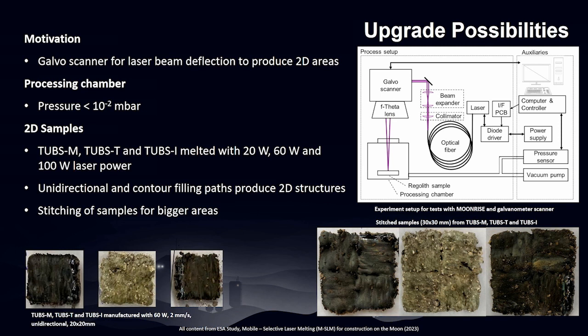One activity of the last year was to see if a galvano scanner for the laser beam deflection is a possible technology to produce two-dimensional areas on the lunar surface for the laser melting without any other moving parts. And therefore, we made tests with several different types of lunar regolith simulants we produced on our own with our regolith system, and manufactured samples in a vacuum chamber.